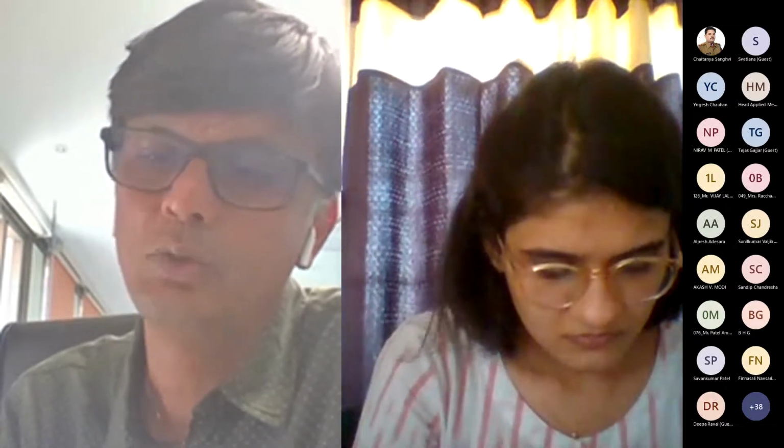That's what Professor Jain was also of the opinion. Professor Durgesh Rai, Veeman Basu and Shvetlana were also part of the team. So we did certain prism tests. We got it tested at IIT Kanpur to arrive at what kind of stress level we can reach. That gave us more confidence about the possibilities in using these bricks. We decided to use 9 MPa bricks, and also cement lime mortar.